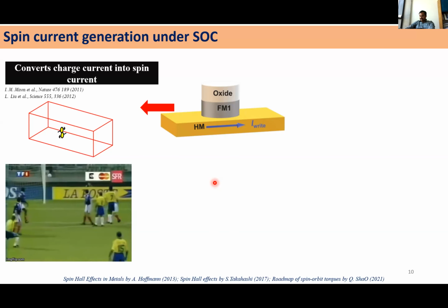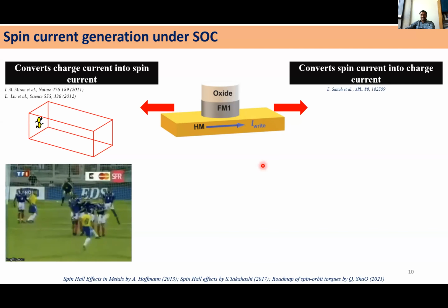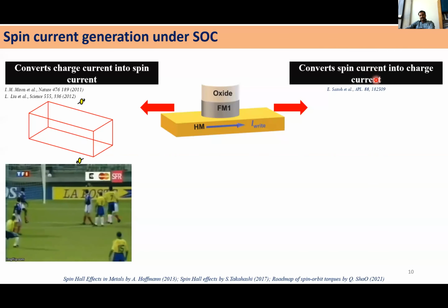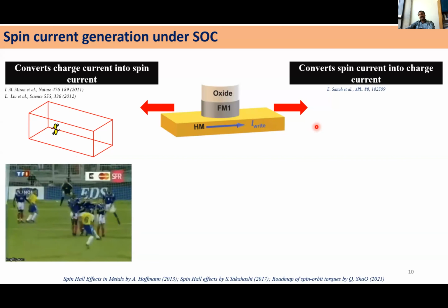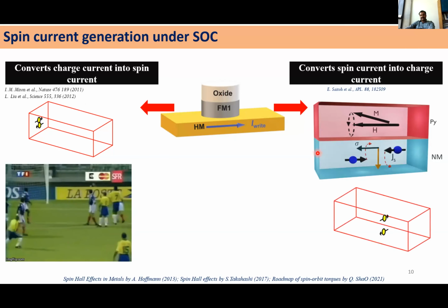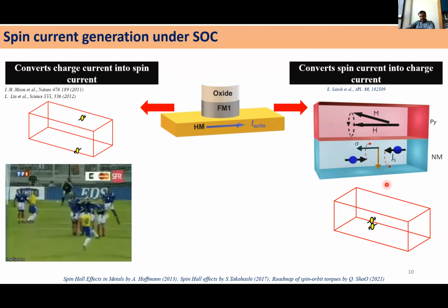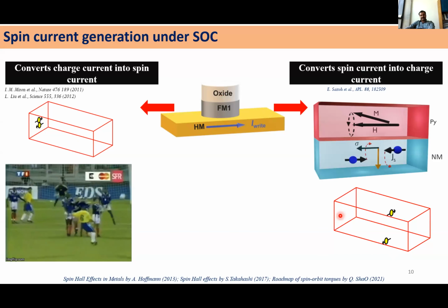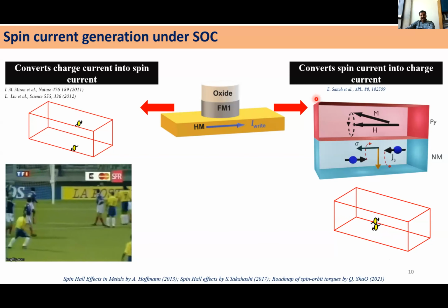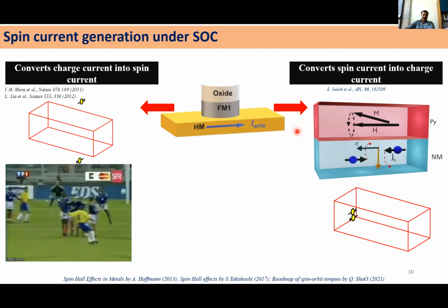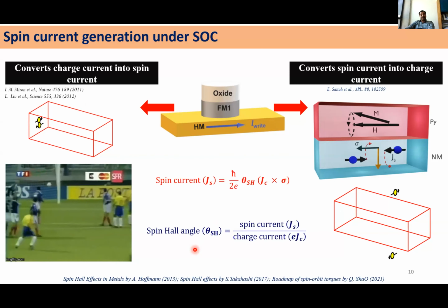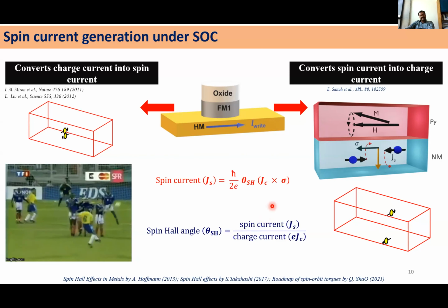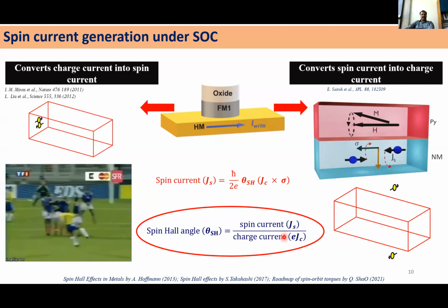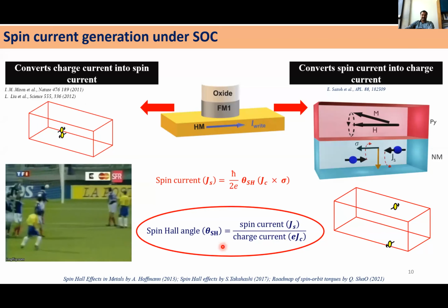As the previous talk has already mentioned, the opposite is also true. When you inject spin current into the heavy metal, it will also be converted into a charge current. So the injection of the spin current converted into a charge current can be seen as a voltage drop across the layer. Either of the methods can help us find the efficiency of the spin orbit coupling, which can be measured by a parameter called the spin Hall angle: how much spin current is generated as a function of the unit charge current. So our interest here is to find out how to tune the spin Hall angle.